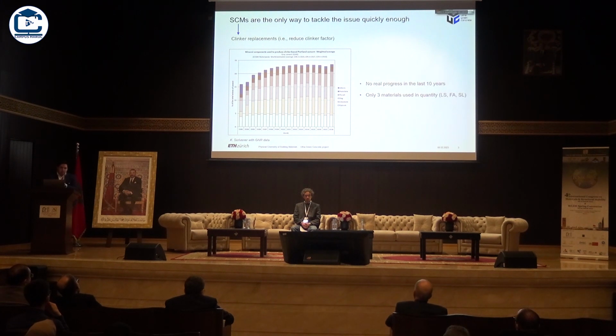So, given that concrete and cement-based materials will remain dominant, clinker replacement, what we call using SCMs to reduce the clinker factor, is recognized today as the most efficient way to reduce the embodied CO2 of cement. But the problem is that in the last 10-15 years, and Karen already introduced this plot, we haven't made real progress on increasing our replacement level.